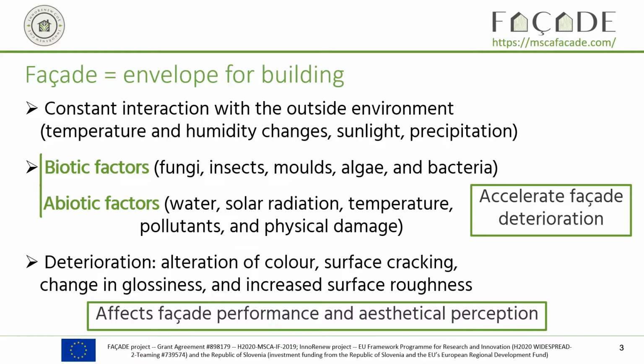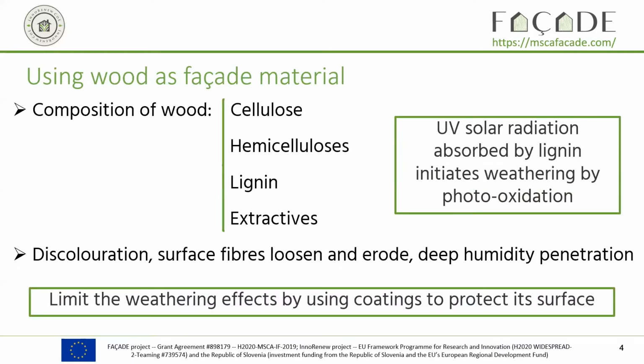And the deterioration will include alteration of the color, surface cracking, change in glossiness, and increased surface roughness. And all of this will affect the facade performance and also the aesthetical perception of the building. This is true for any type of material that can compose the facade, but it is even more especially true in the case of wood, that is a natural material and that is made of cellulose, hemicelluloses, lignin, and extractive, because the lignin will be very sensitive to the UV solar radiation.